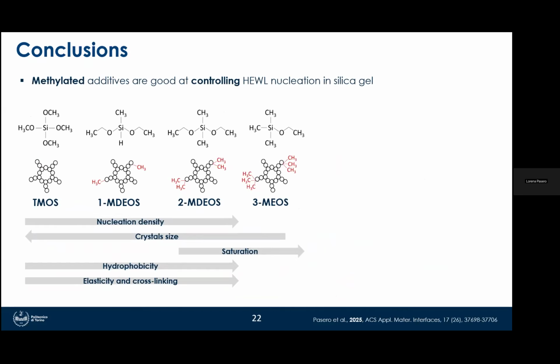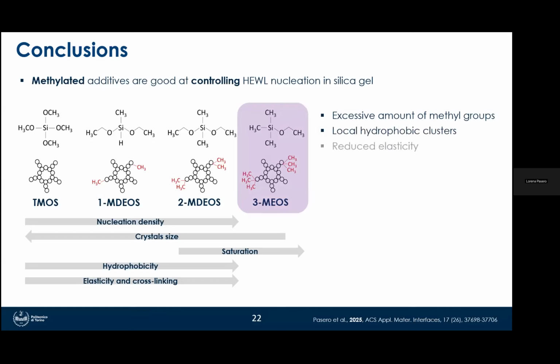nucleation is chemically tunable, but when we increase too much the number of methylation, we obtain an excessive amount of methyl groups, local hydrophobic clusters, and a reduced elasticity of the gel, and so the protein is more, let's say, absorbed on the gel than with 2 methyl groups. So, let's say the nucleation control was valid up to 2 methyl groups, but these results could provide a rational pathway overall for designing convection-free crystallization media and to overcome the limits of silica gels.